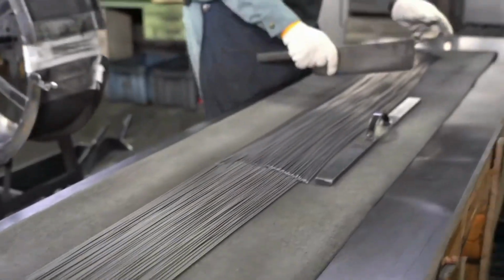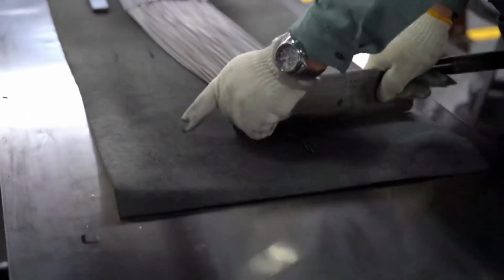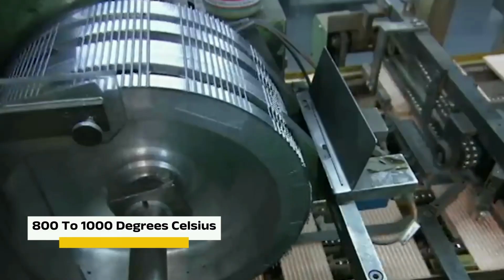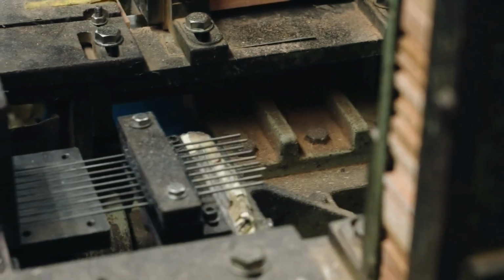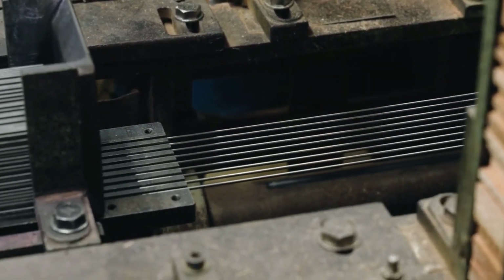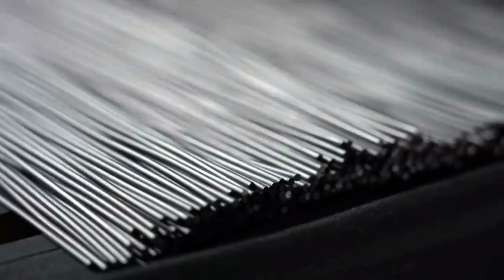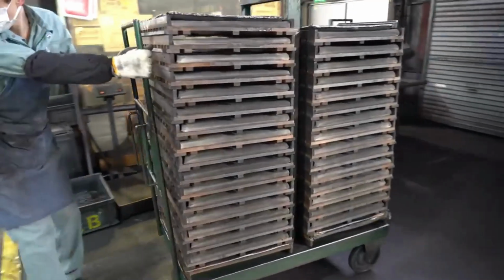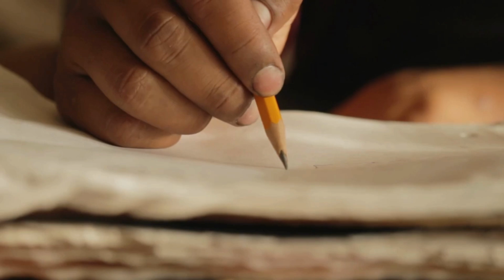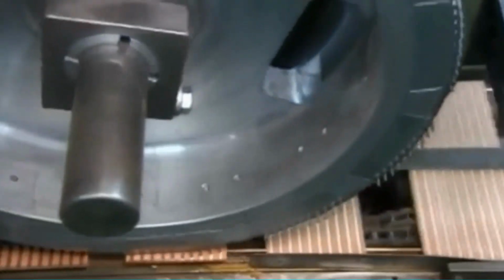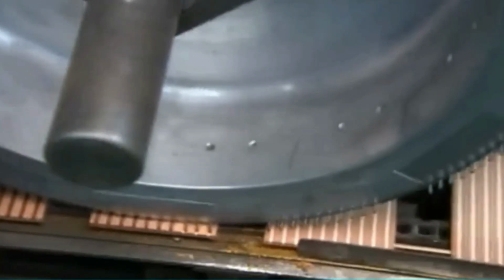Drying comes next. The rods are placed on trays and left to dry until they hold their shape without deformation, but they are still not strong enough for use. To achieve the necessary hardness, they are fired in a kiln at temperatures ranging from about 800 to 1,000 degrees Celsius. This firing process drives off remaining moisture and causes the clay to harden, binding the graphite particles together. After firing, the cores are often treated with wax or oil. This step improves writing performance. The wax fills tiny pores in the material, reducing friction when the pencil moves across paper. Without this treatment, the core would feel starchy and inconsistent.